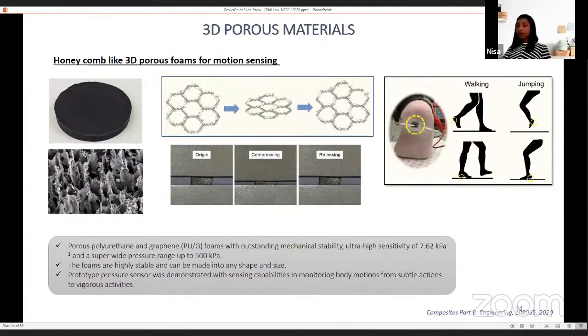Here we combine molecular assembly and also the ordered arrays of structures, such as honeycomb-like features, in a graphene foam. We made a nanocomposite foam by combining polyurethane with graphene. Addition of graphene leads to the formation of ordered honeycomb-like features. These foams exhibited excellent strain sensing properties. We have demonstrated motion sensing capabilities of these materials, like finger bending, walking, and jumping. That shows its potential applications in pressure sensing areas.